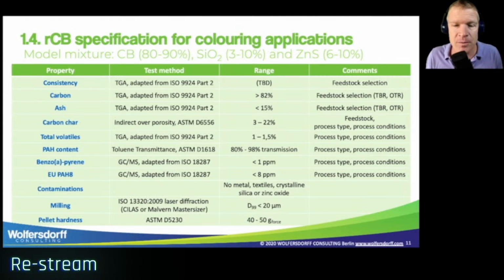We should have no contaminations like metal. We should have no textile contamination, no crystalline silica, and no zinc oxide. And as mentioned before, we should be milling to D99 of 20 microns. And D99 means that 99% of the particles are smaller than 20 micron.